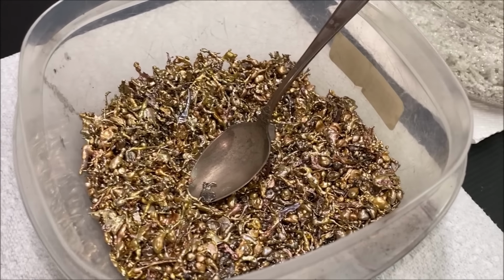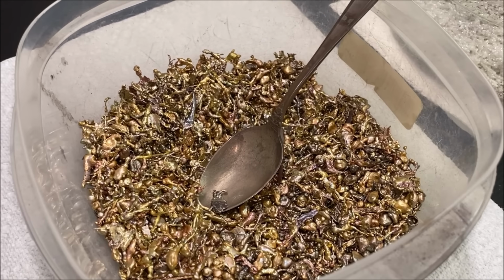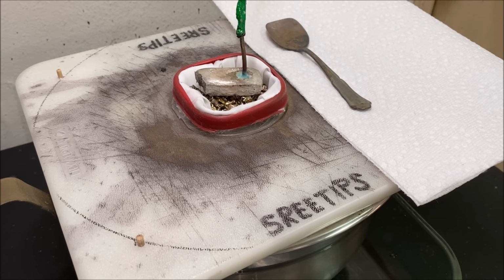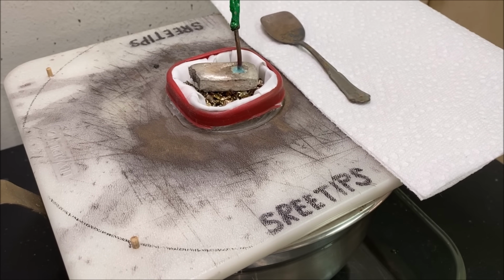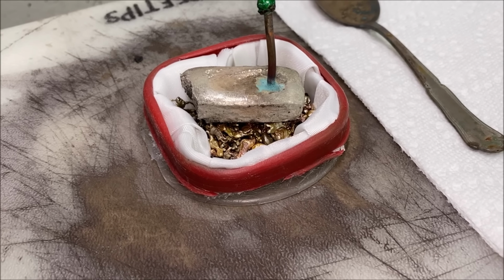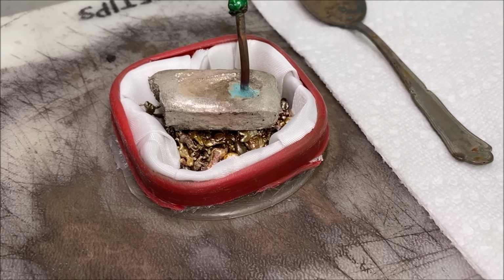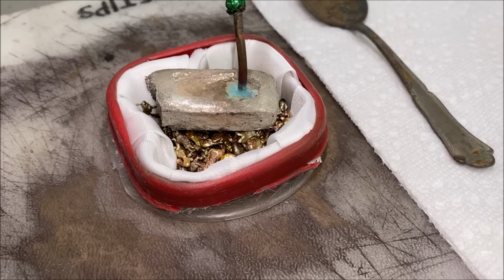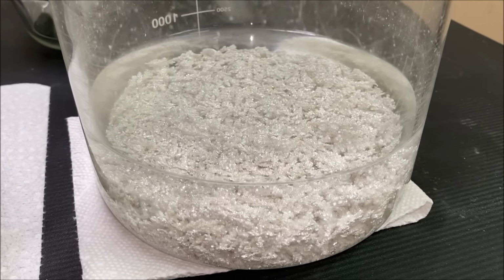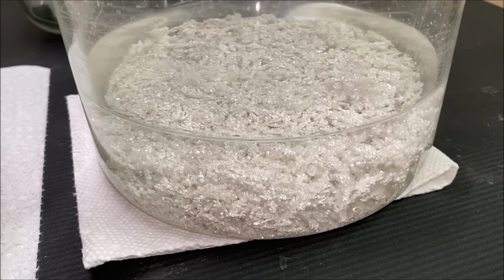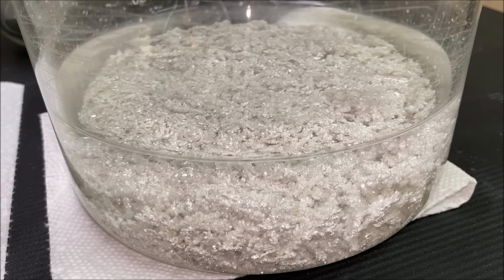So the conclusion here is, we take the impure cement silver that we've melted into granules, feed it into the electrolytic silver cell where it gets dissolved in the anode filter basket. By the way, any other precious metals such as gold and platinum group metals that are in that impure silver will get trapped in that anode filter, and then we save those filters and process those for the precious metals that they contain. And then after about 10 days, like I said, we'll end up with about 1.5 kilos of high purity elemental silver metal.